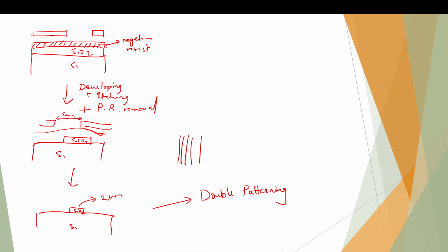Now, in this case we etched all the way till silicon, right. However, if I had only silicon here and after etching I wanted a profile like this in silicon itself, then with the successive processes the other portions will also keep on etching. In this case, because I went from silicon dioxide to silicon, the etch recipe was such that it will not etch silicon, so it will stop the etching process there.